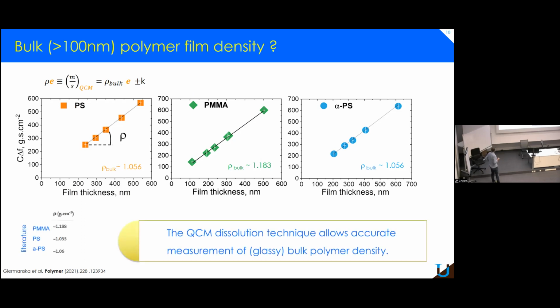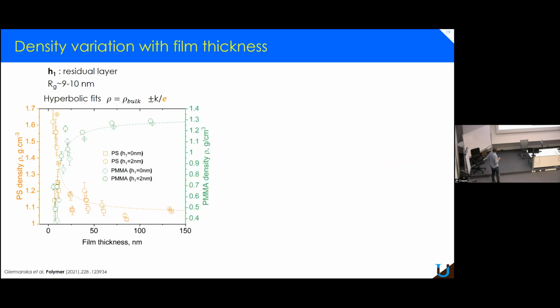And so afterwards, we decided to go to thin films to see what we would get. And this is the wrap up. It took us a lot of time, but here you can see the variation of the PS density on the left and the PMMA density on the right, using the QCM approach. And what you see is exactly what we saw with ellipsometry. This is what we saw with nanoparticle adsorption, but in a direct way.